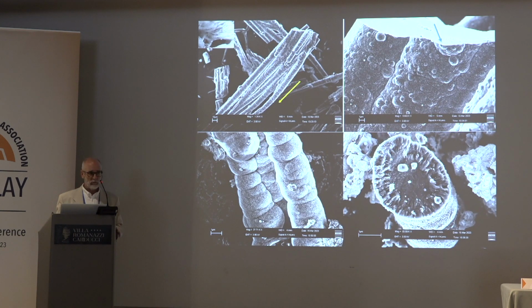We went to the electron microscope. Here I have scanning images. This is a bundle of fibers. The fibers join in this area. This is the growing direction, so it's the flowing direction. The surface has all these protuberances, and really we are, Antonio, at the limit of the resolution of this microscope. The inside is quite homogeneous, so we don't see any structure separating the different fibers of the protuberance. But there are other fibers that are much more beautiful than this one. Here we have a honeycomb structure coating the fibers. And we assume that this is the clay, these curved plates, the saponite.